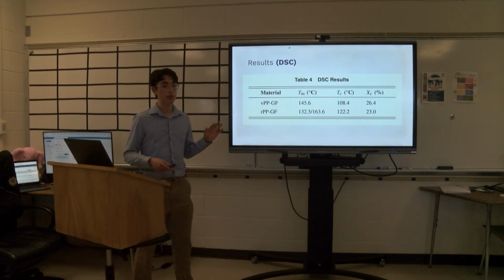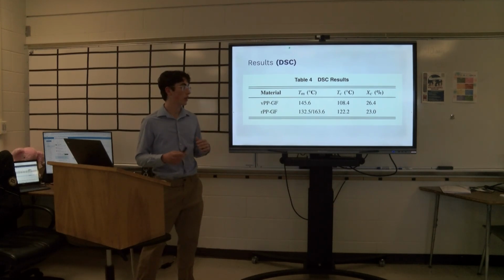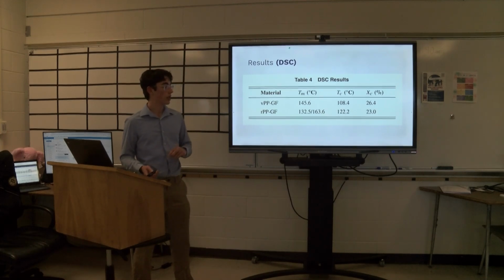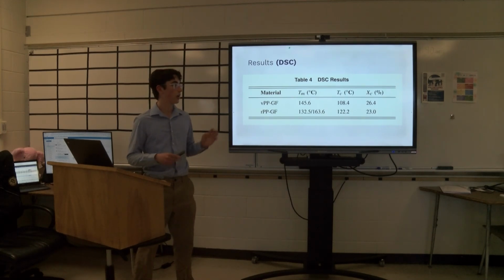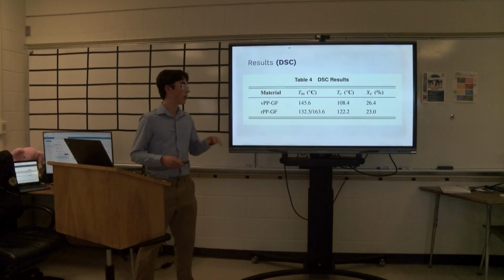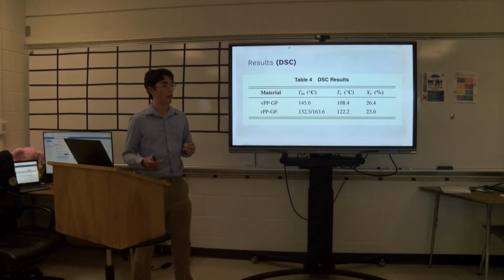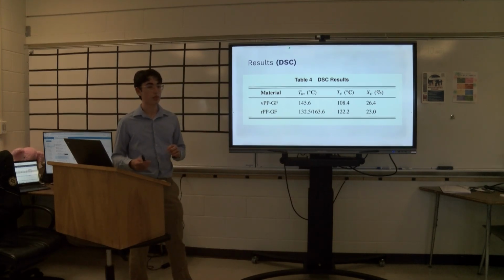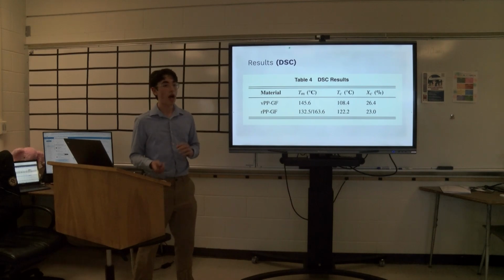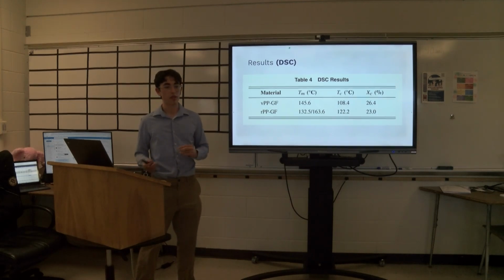Furthermore, the nature of the two peaks interfering made it difficult to construct a baseline to accurately encapsulate the area to calculate the enthalpy of melting, which resulted in a lower enthalpy of melting and thus lower calculated crystallinity for the recycled material. And in light of this, it is not unlikely that the recycled material has similar, if not higher, percent crystallinity when compared with the virgin material.